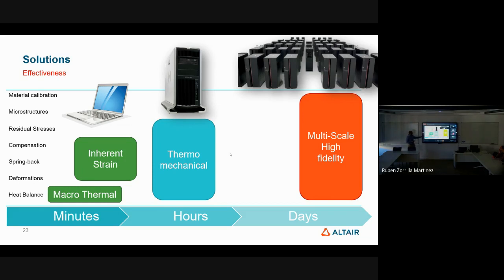And finally, we have another one there. We call it macrothermal. That is not in the product, but we use it internally. This is something that we use just to understand how the evolution of the temperature is going inside, because if the temperature evolution is almost constant, what we can say is that the inherent strain calibration is quite good. If the temperature is going down or going up a lot, then these deformations are not very correct.